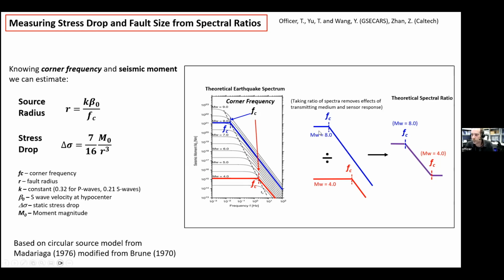So what we do is we take sort of a big event and a small event, and we divide the two. And what you'll get is that at the beginning, before you hit the corner frequency of the big event, you get a constant because they're both just flat. Then you hit the corner frequency of the big event, it starts to go downwards until you reach the corner frequency of the small event, and then you get another constant. So you should get some plot that looks like this.